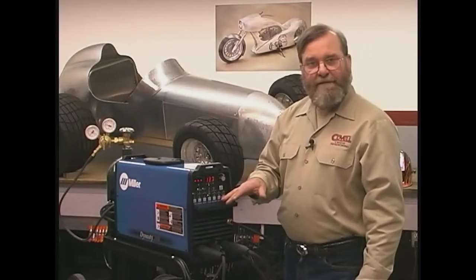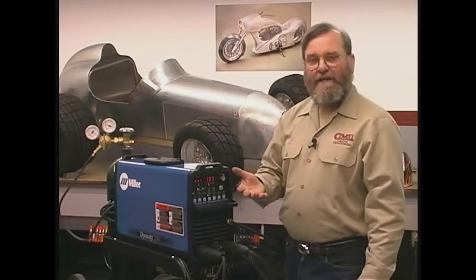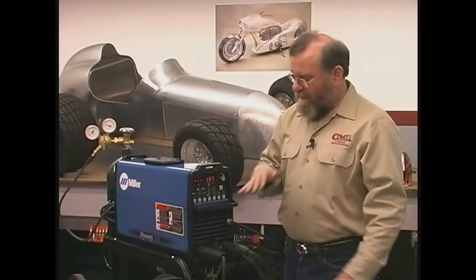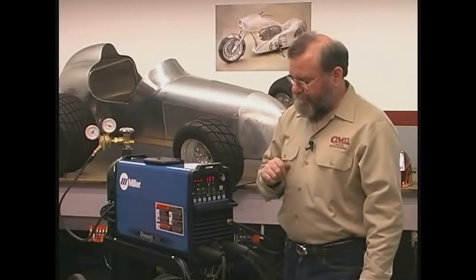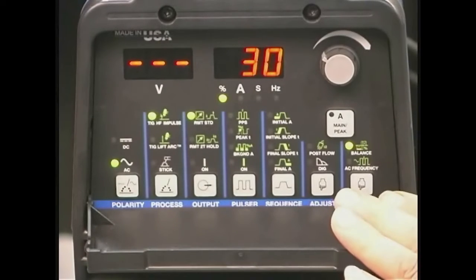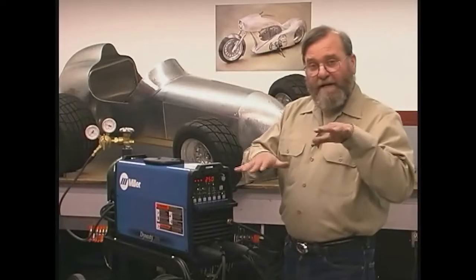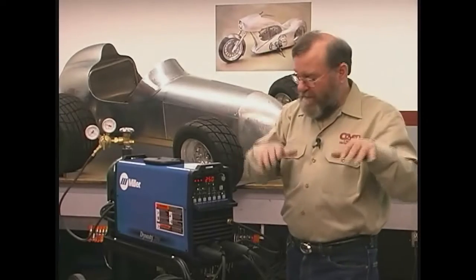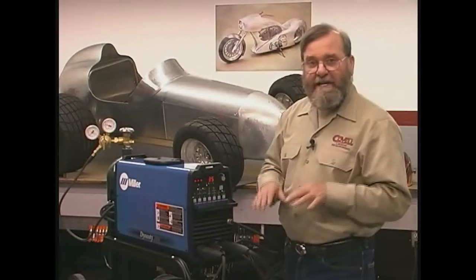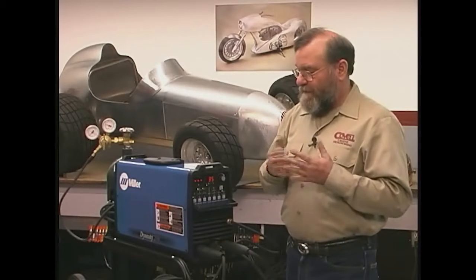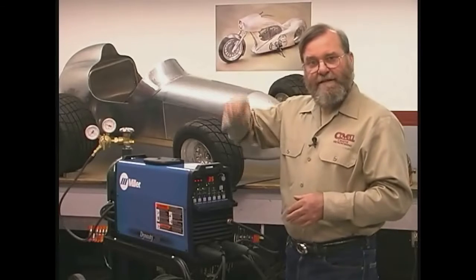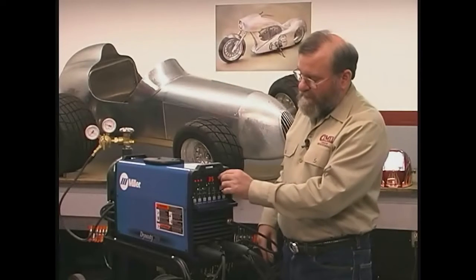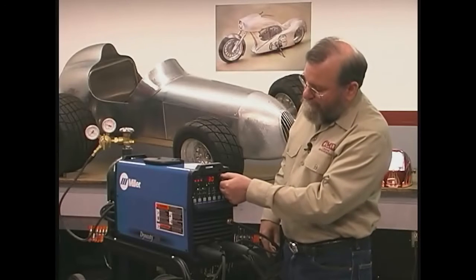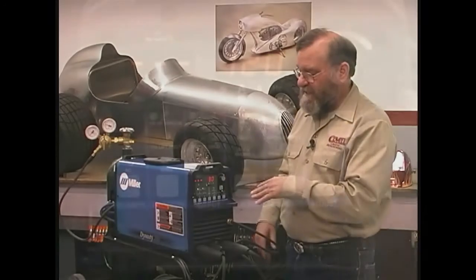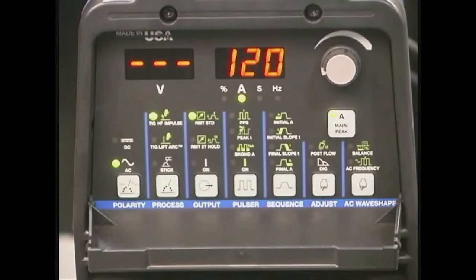A pretty good rule of thumb for this is that we need about 1 second of post-flow for every 10 amps of welding current. So if we're welding at 100 amps, we want at least 10 seconds of post-flow. The button on the right is the one that controls the AC waveform. This is the control we have that balances cleaning versus penetration. And in the other mode, we can change the frequency of the waveform. The older sine wave welders always had a 60 cycle per second waveform. With this machine, we can control all the way from 30 cycles per second to 250 cycles per second, and the higher frequencies develop more penetration.